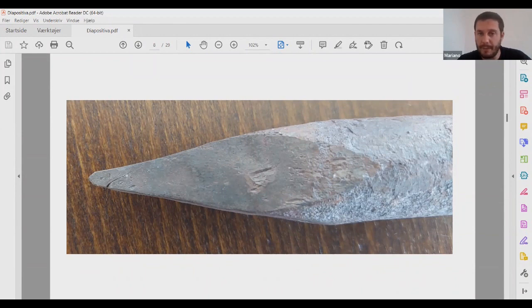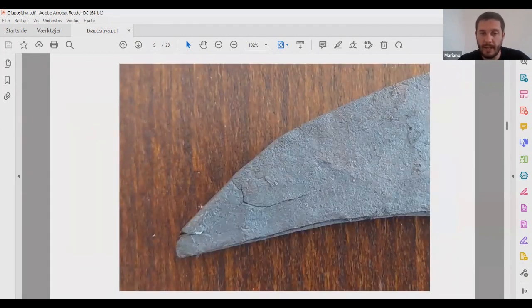This is around 5 millimeters, but we can see here how the cracks, if we keep forging and do not correct this, are like 20 millimeters long. So it's going to start to grow. And for example, if we finish the knife and we temper it, we are going to lose all this part. So it's very important to keep in mind that we have a fresh material.